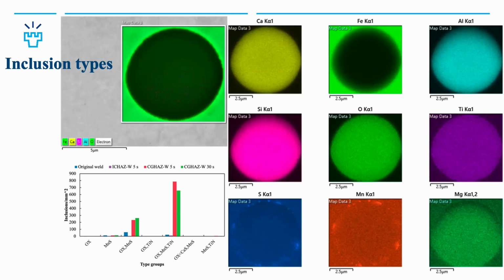And for example, if we have an oxide and there is manganese sulfide on the surface of it, and if the manganese sulfide part grows, then of course the inclusion also grows. And if initially it was below 1 micron, then after this growth of manganese sulfide it exceeds 1 micron, and then we see it here in the results, because 1 micron was the minimum size that we included in the results.